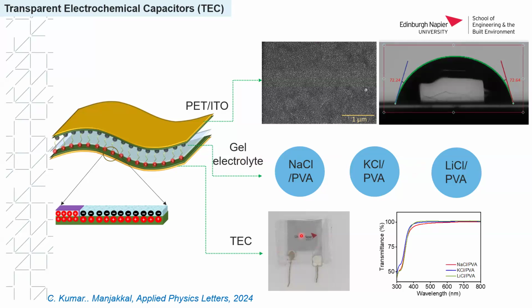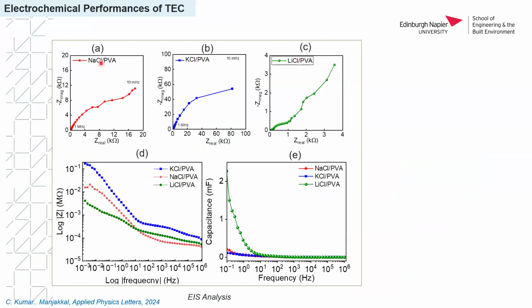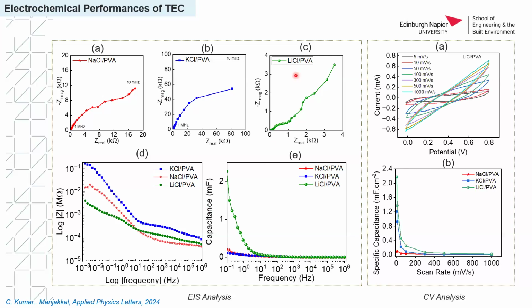It's a fully transparent one. You can see the 100% transparency. Depending on the electrolyte, we noticed that the electrode-electrolyte interaction varies. We observed better performance in the lithium chloride-based electrolyte with PVA as a hydrogel, which shows very low resistance, low impedance and a high capacitance value, because of more ion interaction. You can also notice how the electrochemical reaction, the pseudocapacitance of the material, comes from the ITO. It is a conductive material, but of course the metal oxide is there, so there is a pseudocapacitance reaction.